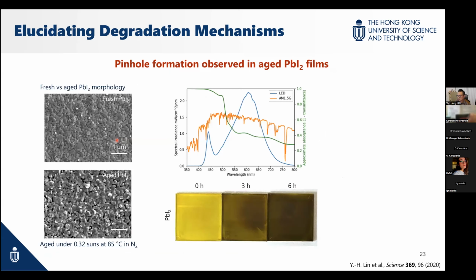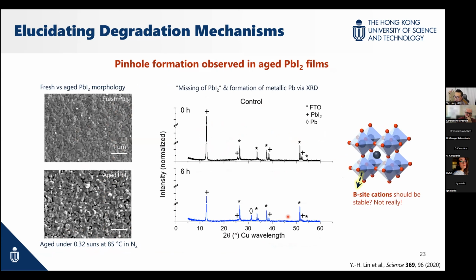So we did a very simple experiment. We took some fresh lead iodide and we aged it in nitrogen at 85 degrees using an LED lamp. It's only 0.3 sun, but in just under 6 hours, you can see it totally discolored. So we did a little bit of study on that. We did some XRD measurement. So we actually see the iodine coming out of the lead iodide film. So basically, it becomes lead. We observe metallic lead in the film and lots of iodide ions.